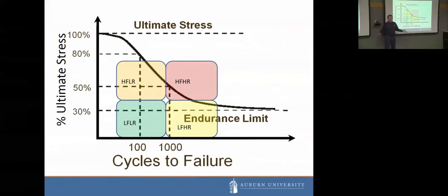So at any rate, that pattern that I just showed of interaction is kind of what you expect to see. So I kind of put the quadrants up here. So low force, low repetition, well below the fatigue failure curve. You would not expect to have a lot of action in terms of musculoskeletal injuries there. Low force, high repetition, well, it depends on how high the low force is and how many repetitions you have. But you would expect to see somewhat of an increase because the fatigue failure curve is diving down at that point, and you may come in contact with that. High force, low repetition, probably a little bit higher than the low force, high repetition is what you would expect